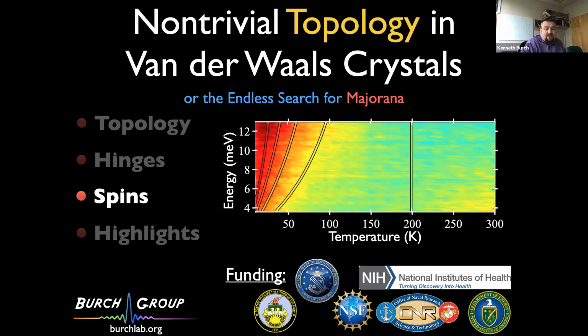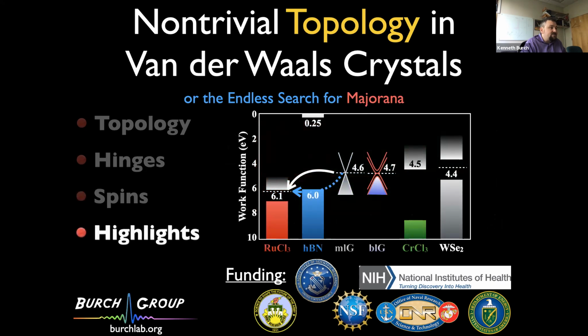So then if I have time at the end, I'll briefly tell you about some new work that's been going on in the group, which is slightly orthogonal, but not exactly. So we found out that this ruthenium chloride, beyond having very interesting magnetic interactions, also has another kind of remarkable property, which is it has this extremely deep work function. So its work function is 6 electron volts. And I'm comparing it here with a variety of other 2D materials. But it's not enough that it has this deep work function. It also has a very small gap because it's a relativistic Mott insulator with a very narrow conduction band. And so what that means is if you put monolayer graphene on top of it, you will have an enormous amount of charge transfer.